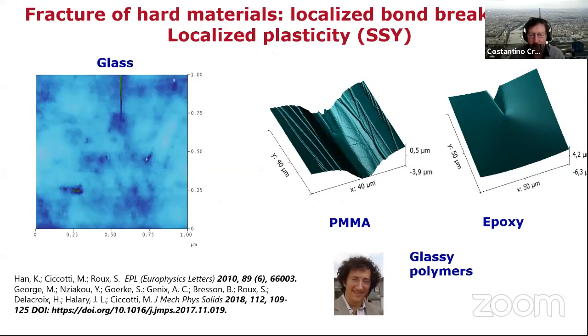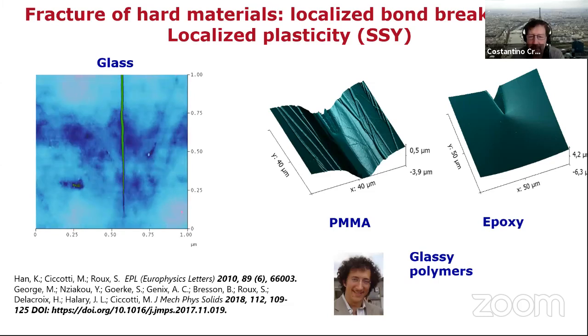So first, a little introduction for students attending. Fracture, the typical fracture that you learn in graduate school, will be about linear elastic fracture mechanics, about brittle material, where a chemical bond is very localized. So you don't really have to worry about it for your material property. In glass, it's extremely localized. So here's an AFM picture from my colleague, Matteo Ciccotti. And on the right, you see an AFM picture of PMMA and epoxy, where you can see also some local plasticity. But in any case, in this type of hard material, you have an elastic behavior everywhere, except very locally close to the crack tip.